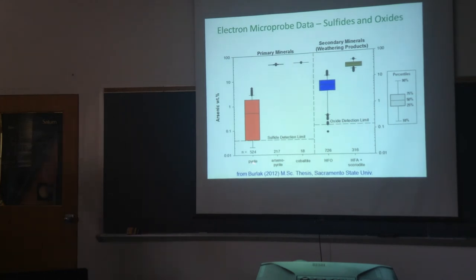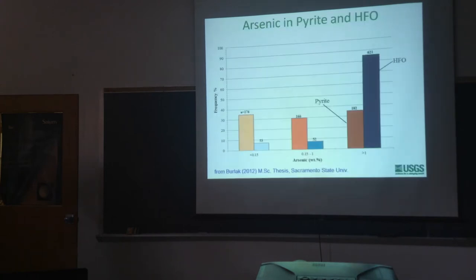So when Tamsin did her work, we looked at just overall pyrite content, the arsenic in the pyrite. We also looked at arsenopyrite and cobaltite, which is a cobalt arsenic sulfide. And of course, those are up at 40% arsenic, and the pyrite has this range. The HFO and the HFA, I said, it's kind of an arbitrary division at about 18 weight percent. And so we had quite a bit of this HFA material that had 20 to 40 weight percent arsenic in addition to the hydrous ferric oxides. We split them into low, medium, and high in both the pyrite as well as the HFO itself, just as a way of mapping things out.